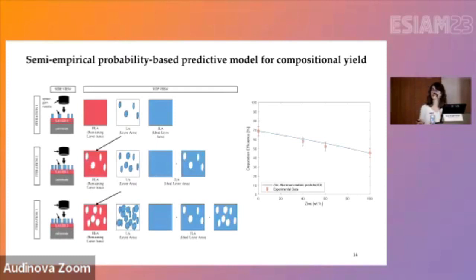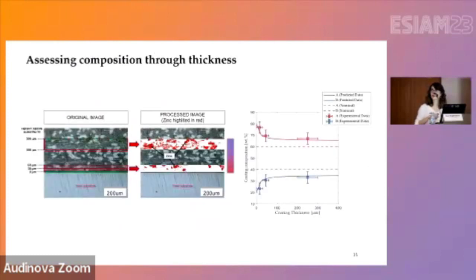Here you can see the results of application of this model to a specific combination of zinc and aluminum for 4 different chemical compositions. The results are in very good agreement with the experimental measurements. And also here you can see the results in terms of capturing the variation and evolution of chemical composition as we are getting far from the substrate.